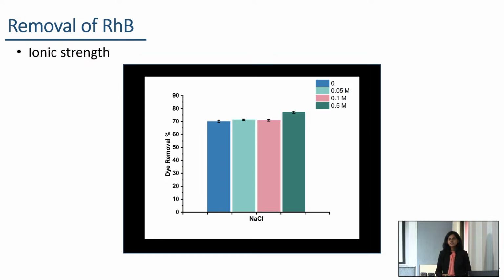So, then the ionic strength effect on the removal of rhodamine B was measured by adding different concentrations of sodium chloride. Here we can see that at low concentrations of sodium chloride, there is no significant variation in the dye removal process. However, at high salt concentration, we can see a significant increase in the dye removal process.